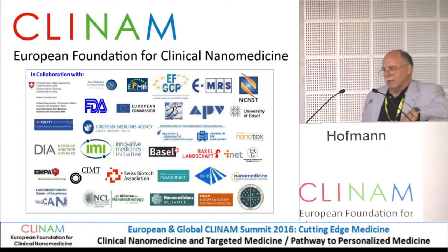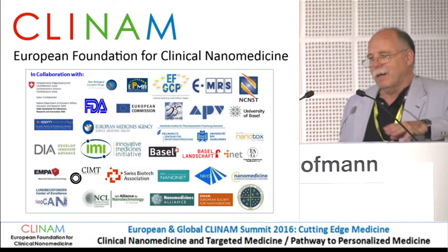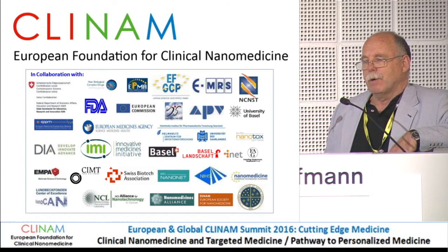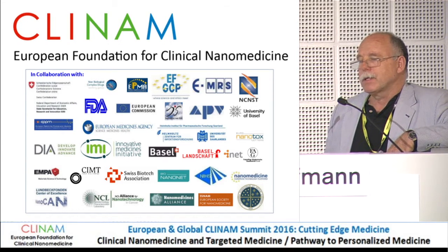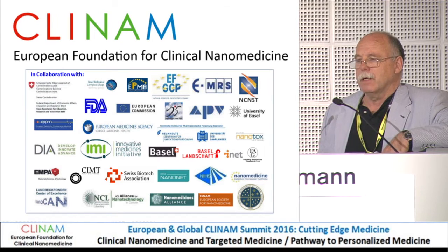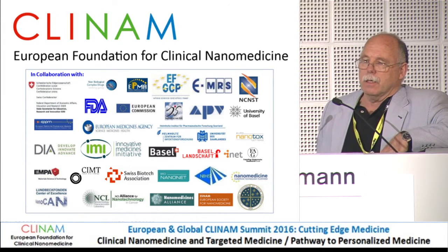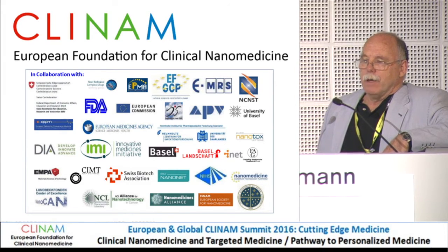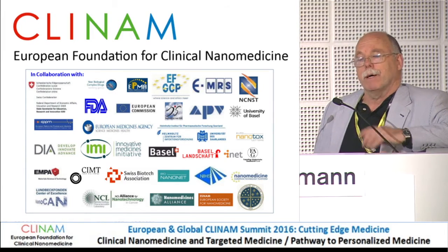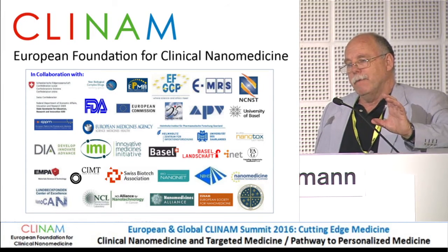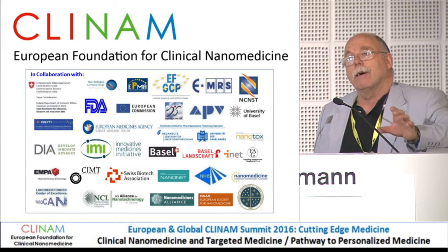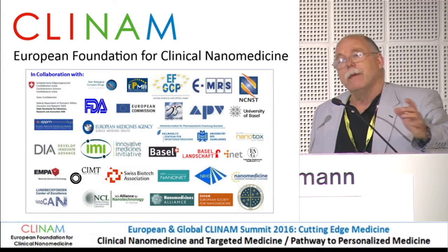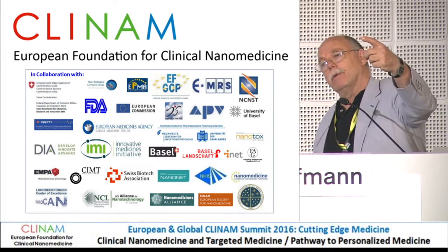I think so. I have no final clear answer to this, but if you look at all the results we have, with endosomal uptake it is not really a problem. Then mostly we do not have this ROS production. If the particles are in the liver, normally we have no problem. But the main thing is we need Fe2O3 if possible, and not Fe3O4, because this is very important. Even if we reduce the magnetic properties, we gain in biocompatibility.